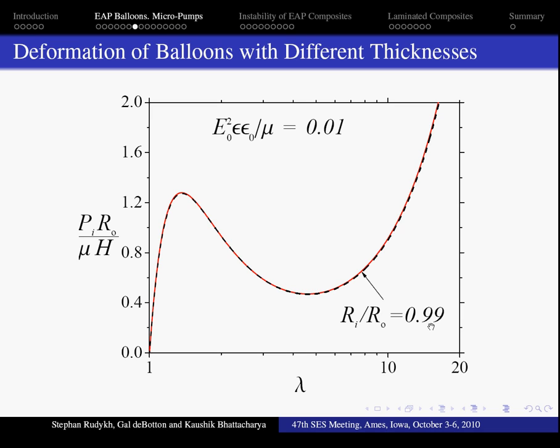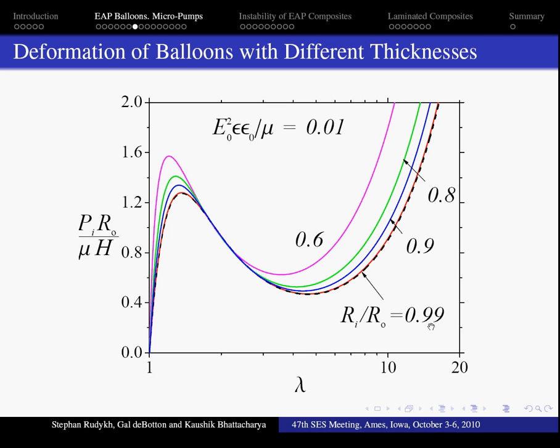But with increase of the thickness the difference increases. For micro-actuators with a diameter of a few tens of micrometers the thin-wall approximation will lead to considerable errors.